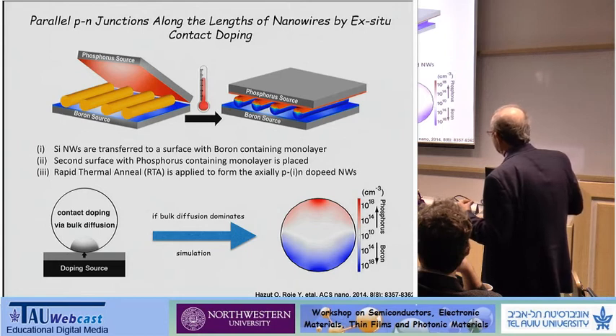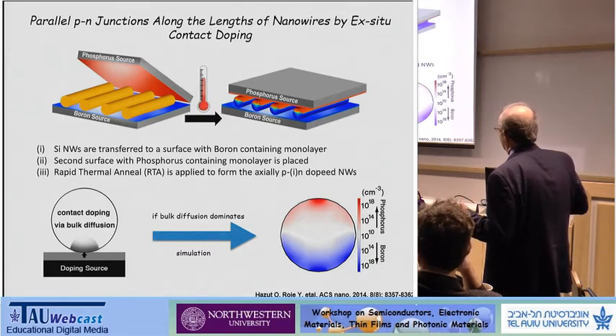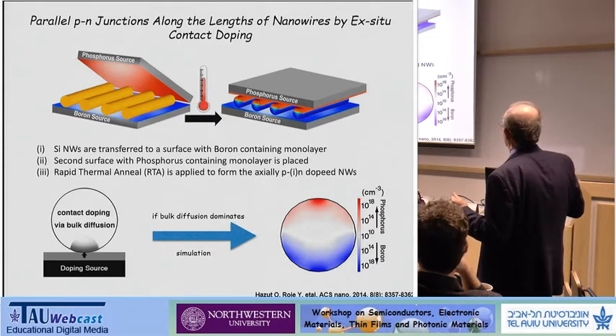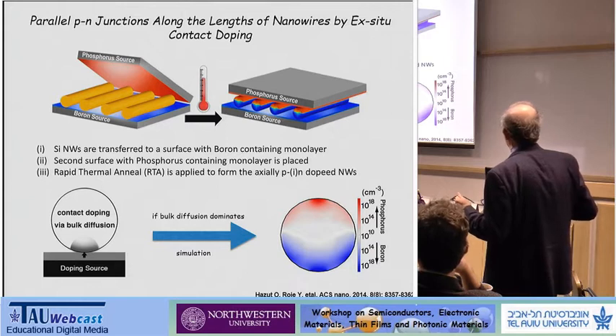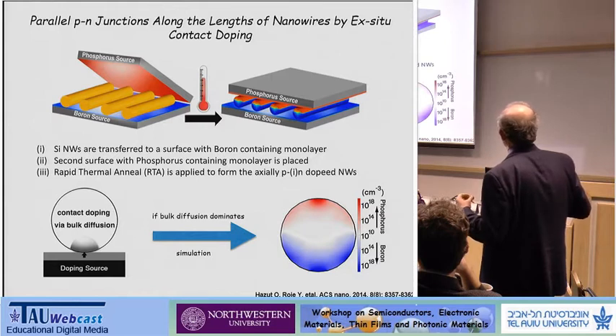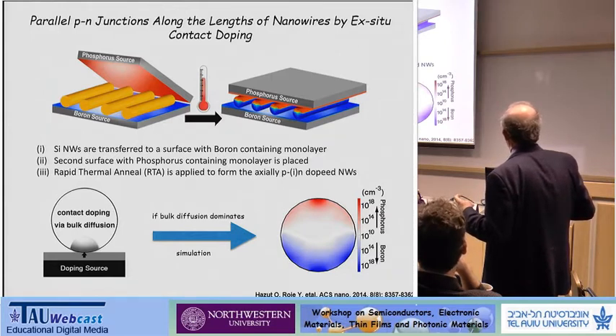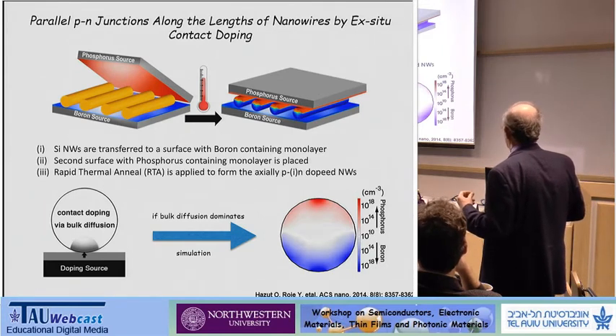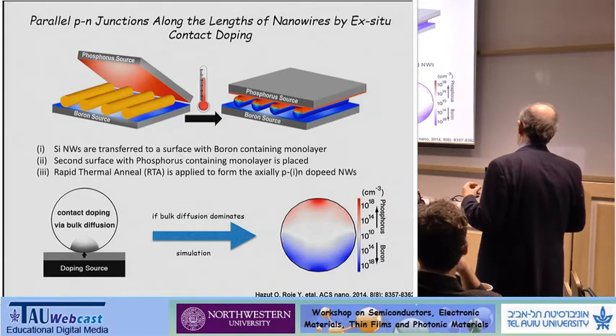And this is just a schematic of what's happening on the boron side. You can see the source here corresponding to 1 monolayer. It's an organic compound that produces a 1 monolayer of boron. And then it can diffuse in when you heat it. When you do rapid thermal annealing, you can heat it. And this is a simulation of the distribution that you would expect. This is the phosphorus, and this is the boron. At this temperature of the rapid thermal annealing, the diffusivity of the boron is 1,000 times greater than the diffusivity of the phosphorus. And this is from Roy's group. And this is his graduate student, Ori Hazut.